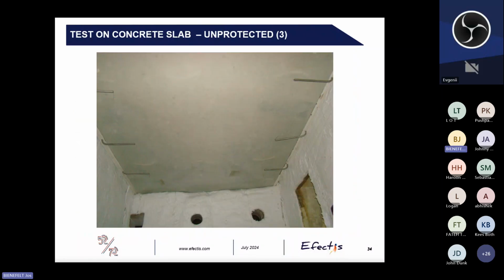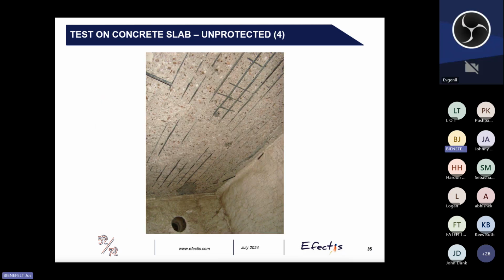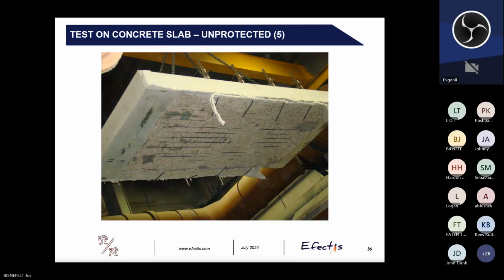This is a picture from inside the furnace showing the underside of the slab before the fire test. And this is the result after 25 minutes of RWS fire curve. So spalling in this case was so severe that we had to stop the test prematurely. This test actually had to run for 2 hours. This is again a picture giving an overview of the amount of spalling.